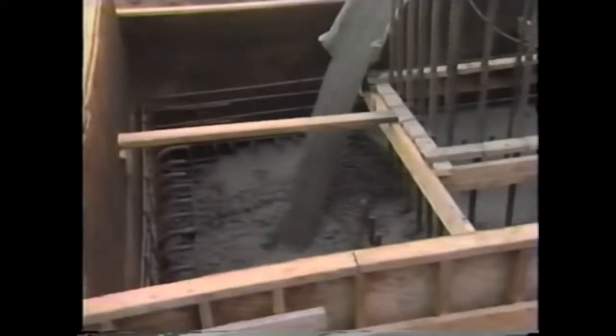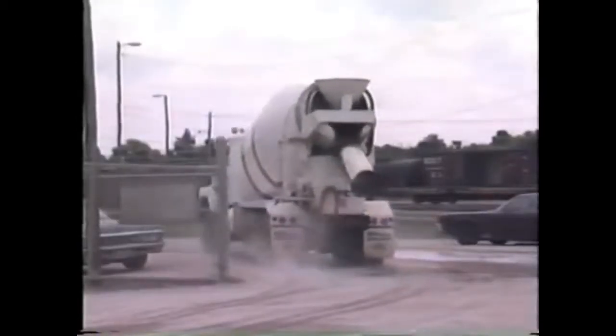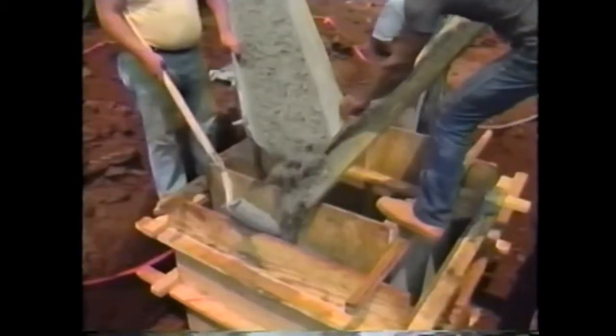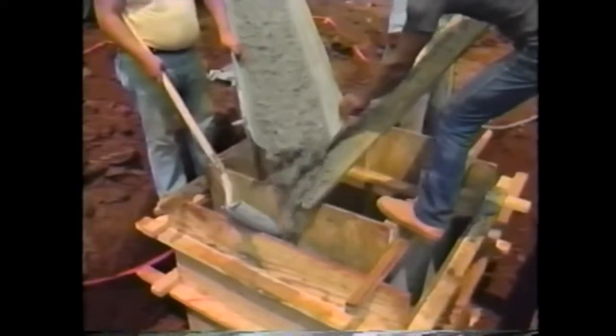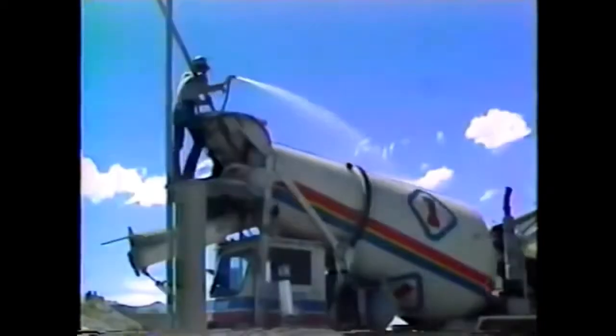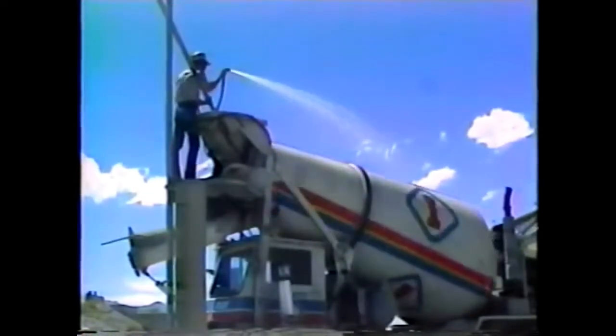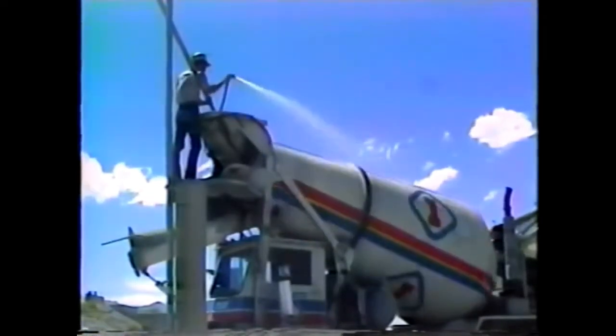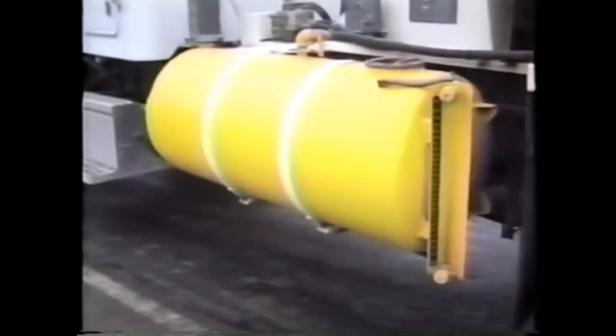In practice, however, the concrete ordered for the job may not be the concrete that's actually placed. At critical points during production, transport, or handling on site, the concrete's quality may be jeopardized. Batcher mixer slips are not always a guarantee that you have the right concrete in the truck. For example, if wash water was left in the truck before it was loaded, the mix may be too wet. Or the truck driver may decide to add water if the mix begins to stiffen.